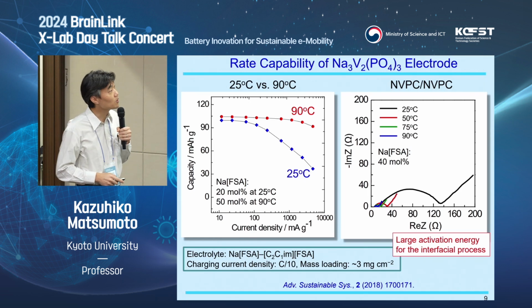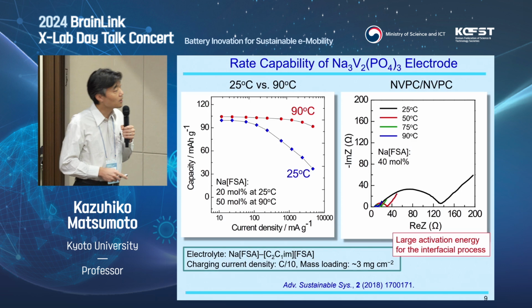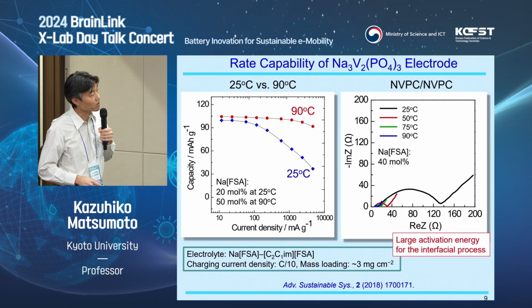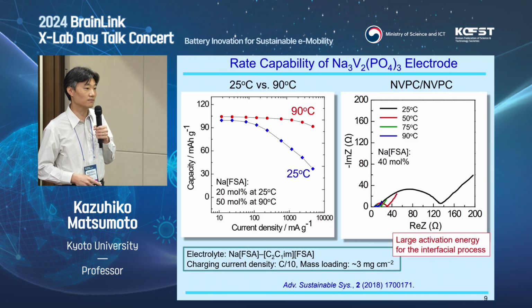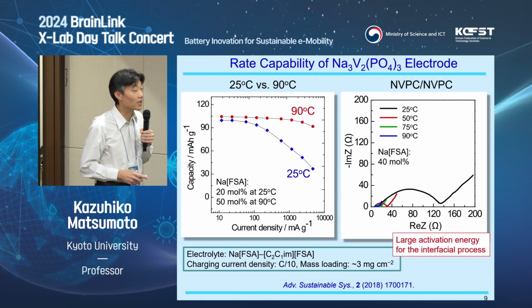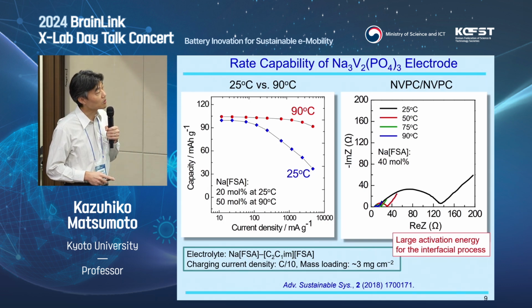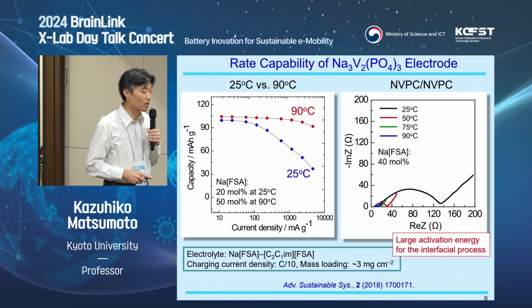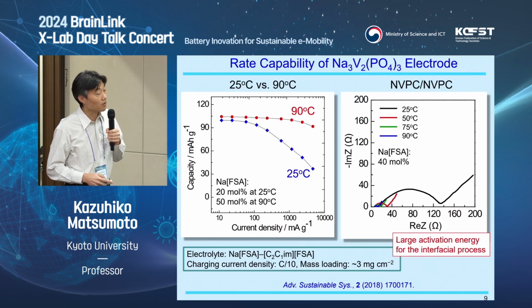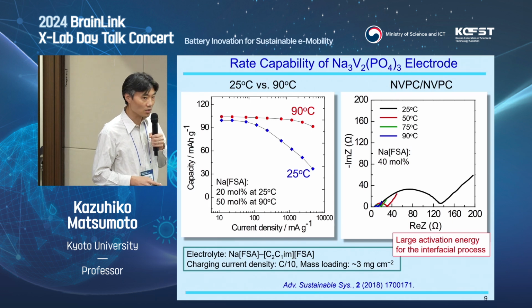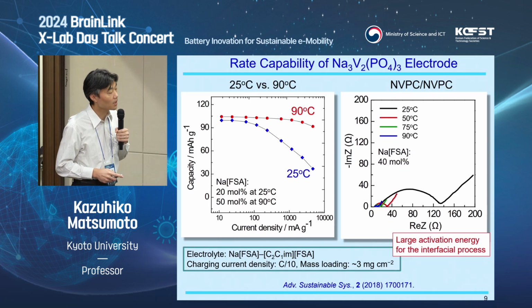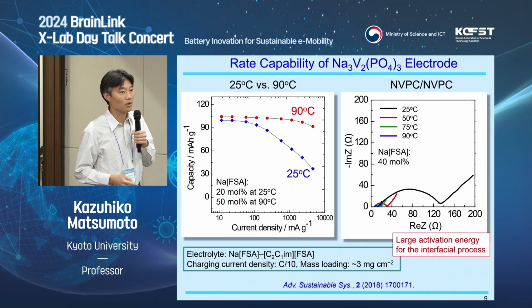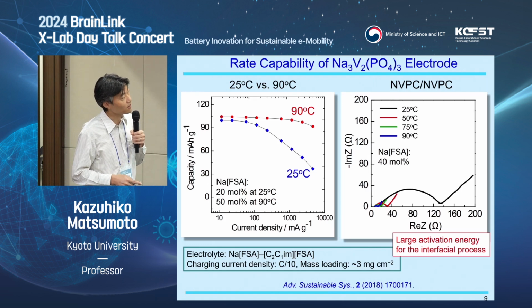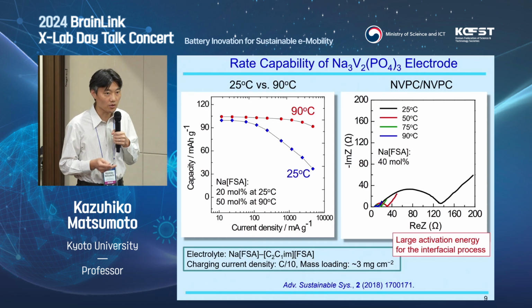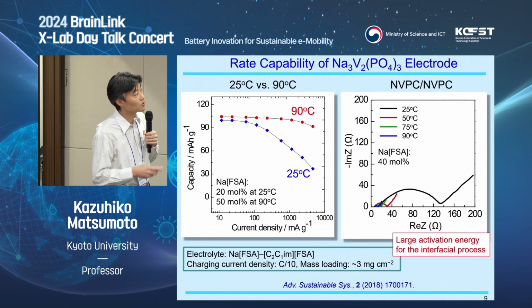The other example is the rate capability of electrode materials. Here I'm showing the Na3V2(PO4)3 type, NASICON type positive electrode. The left-hand side is the rate capability test, where when we increase current density, the capacity usually decreases. This is a typical behavior at room temperature, but at 90 degrees C, we see only a small drop of capacity, even at 4,000 milliampere per gram. And of course, we expect fast ion diffusion. But not only that, when we take a look at the Nyquist plot of that NVP symmetric cell, the semicircle corresponding to interfacial process decreases very largely from 25 to 90 degrees C, suggesting not only ion transport, but also interfacial electrochemical reaction is really enhanced as you go up to 90 degrees C.